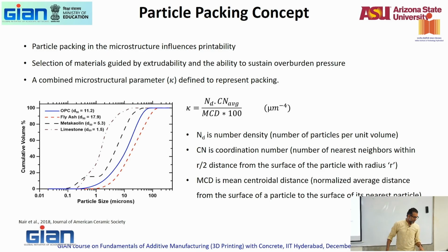So you can look at a few of these microstructural terms: number density, coordination number, and mean centroidal distance. Number density is the number of particles per unit volume. As the size goes down, number density goes up. Correct? Coordination number is the number of nearest neighbors within a certain distance from a particle, which means if I take a cement particle, how many nearest neighbors do I have? And who are my nearest neighbors? If my cement particle has all the nearest neighbors as reactive particles, then my cement has to work hard in that area to do it.